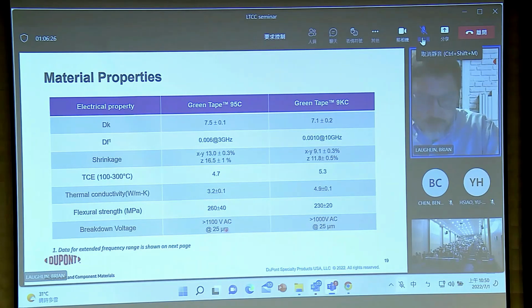So in the end, I want to start transferring from LTCC process in general to our specific material systems. And so I made allusion to it before. We have 95C and we have 9KC. 95C is lead containing, 9KC is lead free. They have different dielectric performance and material performance, and they're suited for different things. So 95C has a slightly higher dielectric constant of 7.5, and it has a loss of about 0.006 at about 3 gigahertz. Contrast that with 9KC, which is a slightly lower dielectric constant, but where 9KC really shines is a very low dielectric loss. So on this data table, 0.001 at 10 gigahertz, which is kind of our QA level. And I'll show a more frequency graph in a moment.